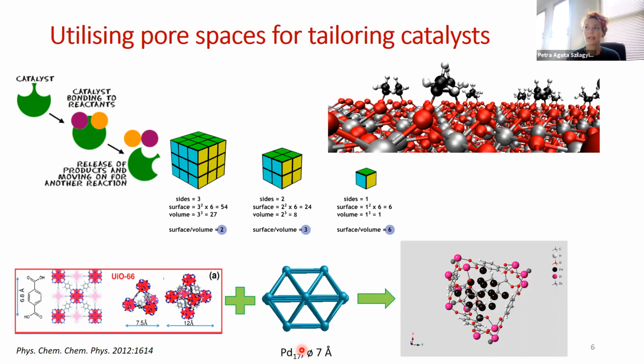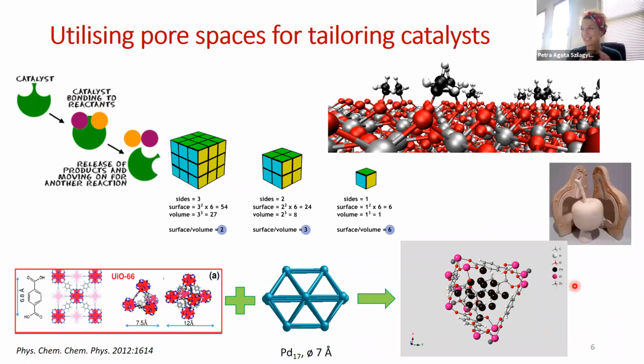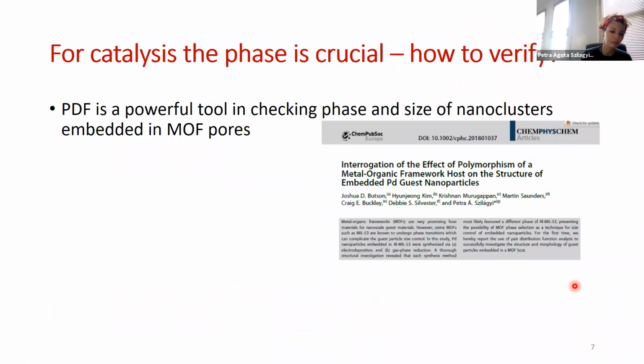But I should point out that this is really not the approach we're actually using to embed the metal inside the pores. We rather infuse a precursor of the metal of choice inside the pores, and then reduce it and allow the cluster to grow inside the pores of the metal organic framework. So this is the idea, that it really is a template, and so, at least in terms of the size of the cluster, we would replicate the size of the pores.